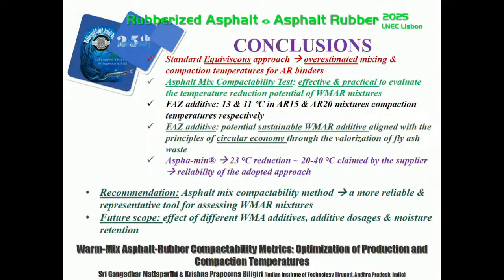So the asphalt mix compactability test that was proposed was effective and practical to capture the temperature reduction potential when we use the foaming additives. One more key takeaway from this research is that the fly ash additive that was developed contributes to the circular economy through the valorization of fly ash waste.